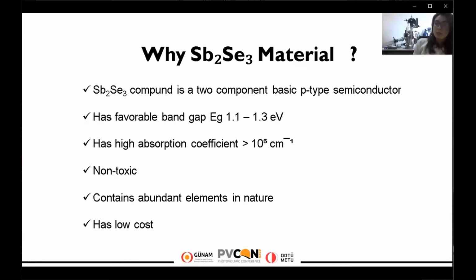Actually, antimony selenide compound is a two-component basic P-type semiconductor. The CIGS, copper indium gallium diselenide, cadmium telluride, CIS, these commercially take part as an absorber layer in thin film solar cell production, but cadmium is very toxic, and indium and tellurium are very expensive due to their limited underground reserves, and it's very costly to make them usable.